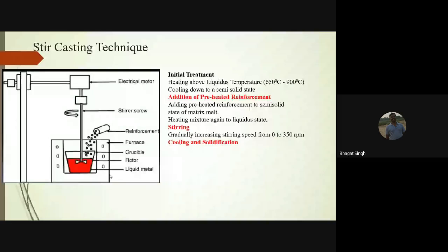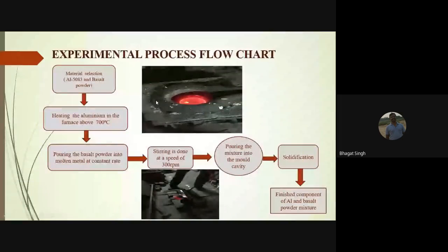Once the molten aluminum was ready, we added the basalt powder. Once the stirring is happening, the basalt powder is mixed homogeneously, after stirring for nearly 15 minutes. So this is the setup. Once the aluminum is melted and we have added the basalt powder, after that we poured it into the die. We followed the same procedure for all 3 compositions. We took the basalt powder at 0, 5 and 10%, and poured into this rectangular die.